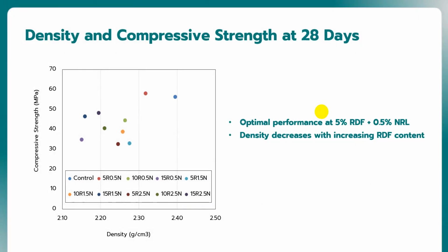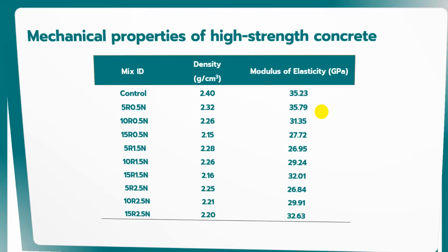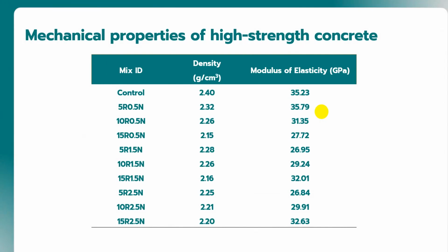We also tested the density and compressive strength, and we found optimal performance at 5% RDF and 0.5% NRL. And the density decreases with increases in RDF content. Here is the density and the modulus of elasticity.